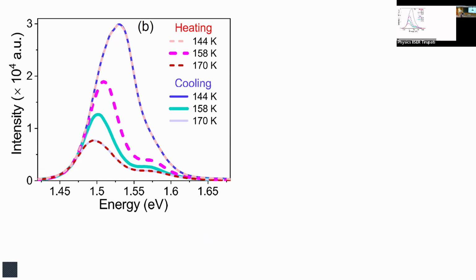So we are going to look at the photoluminescence, and these materials also have a first order phase transition. At room temperature, 300 Kelvin, it's in the tetragonal phase. At low temperature, below 160 Kelvin, it has an orthorhombic phase. It's a first order transition, there's a hysteresis associated with that. We were trying to follow this phase transition through the photoluminescence intensity and shape. So we are going to cycle through. We'll start with 144, heat, go to 158, heat, go to 170. Then we'll start to cool, come back to 158, the same temperature, cool further to 144.